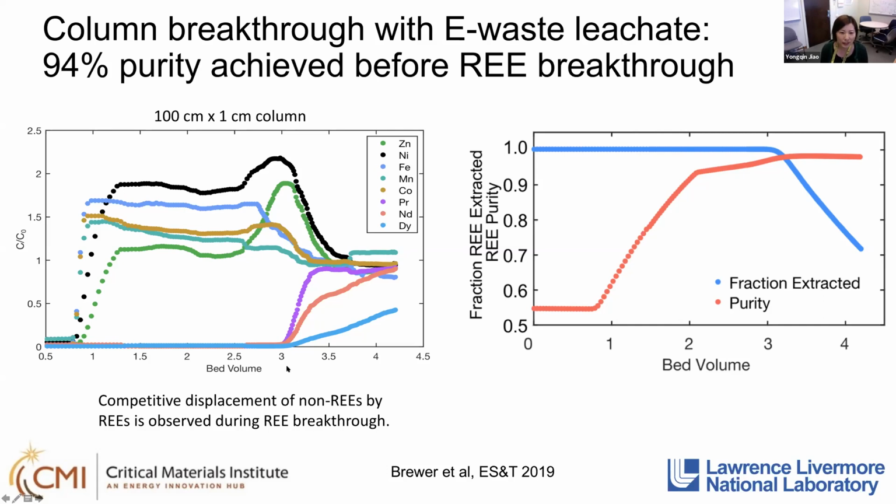And the third observation is that the breakthrough time of the rare earth metals all occur at a similar time, although with different slope, indicating that this absorption-based approach is not likely to be an effective method for rare earth separation.